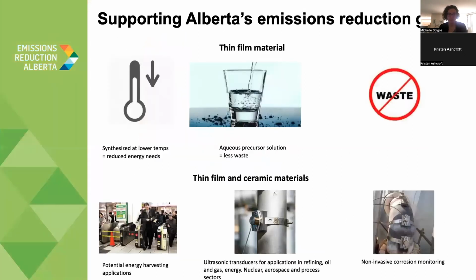Next slide, please. So the ways that this supports Alberta's emission reduction goals is that we've been able to come up with an environmentally friendly synthesis technique for our thin film. It's synthesized at lower temperatures, and the annealing time goes from an hour to about a minute. So we have significantly reduced energy needs to make these thin films.